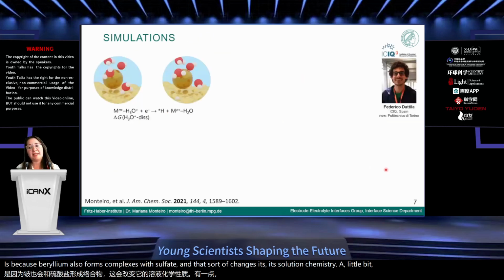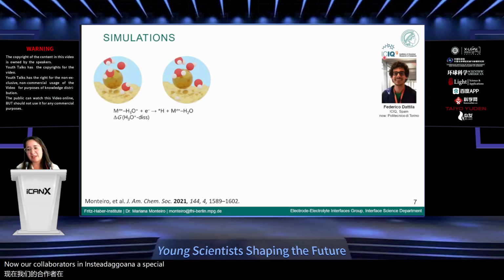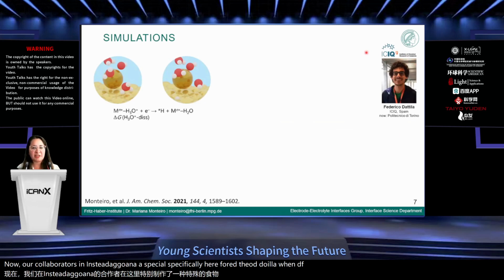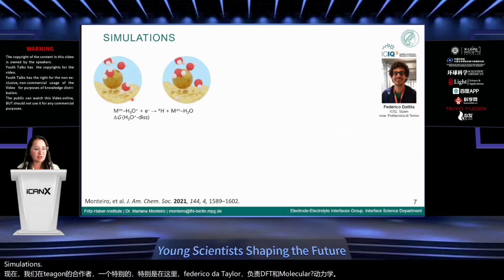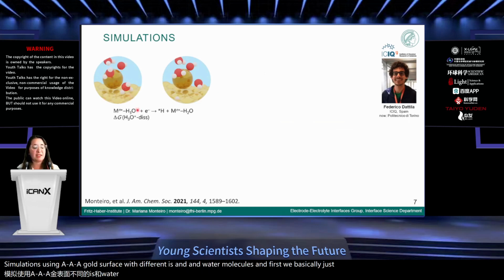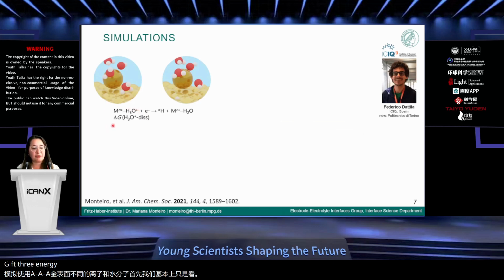Now, our collaborators in Tarragona, specifically Federico Dattila, ran DFT and molecular dynamics simulations using a gold surface with different ions and water molecules. First, we looked at the Gibbs free energy for hydronium dissociation. You see here snapshots of two different states of the simulation.